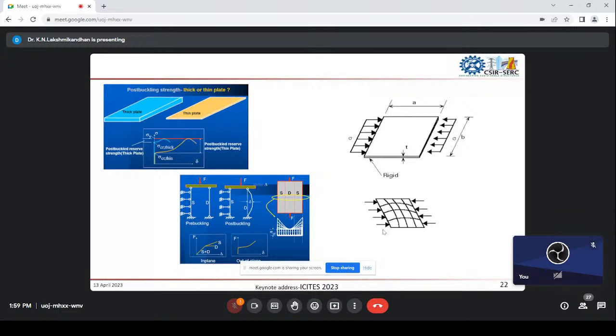Now come to the strength aspect. Ferrocement panels are very thin elements. If you apply a compression force, it will take the compression force until it reaches the critical stress value. Once the critical stress value is reached, because of the thin section, it buckles. When the plate starts to buckle, the post-buckling strength is reached, which gives more strength compared to what we normally design for in plain concrete or RC concrete.